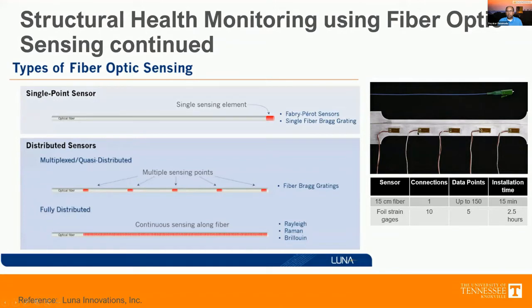The requirements for strain gauges are, of course, you need to be able to connect them, you need to be able to mount them, and you need to make sure that if you're trying to use them underwater or exposed to a saltwater environment, they are properly protected. And you can imagine that just in this example, if I'm looking at a 15-centimeter span, we want roughly 5 strain gauges, that installation would take about 2.5 hours, and we only have strain averaged on the gauge length at these 5 locations.